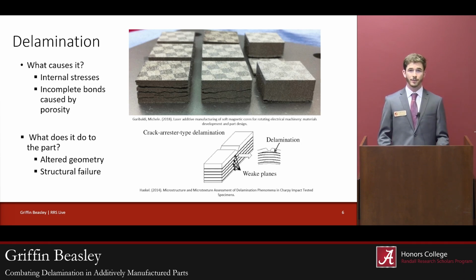As for what this does to the part, the most obvious thing is that as the layers pull apart from each other, the part itself begins to change shape and it no longer matches the provided three-dimensional model. This means that the previously expected accuracy and tight tolerances are no longer present in the finished product. But more importantly, after delamination occurs, a complete structural failure occurs inside the part, meaning that parts that experience delamination can no longer hold any kind of load without further delamination or complete breakage occurring. This means, with how common delamination is, that most additively manufactured parts cannot be reliably used in a high-stress environment.